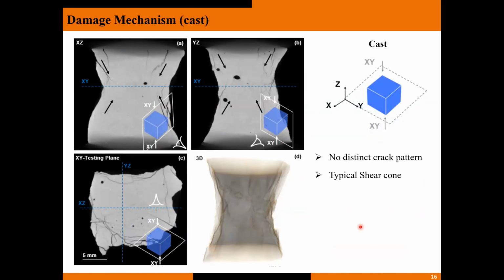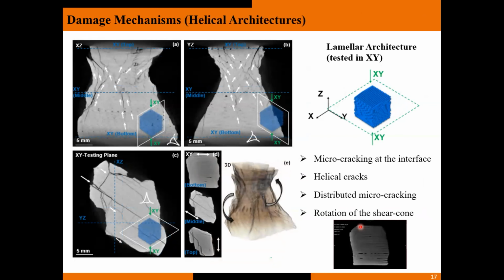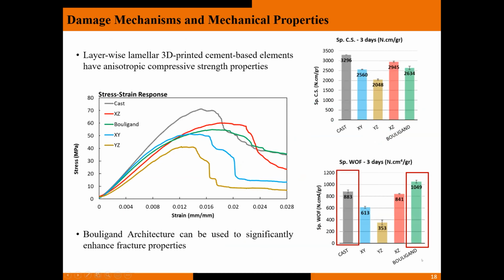Then we focus on the damage mechanisms in these samples. As in cast, there was no distinct crack pattern, just localization of a crack in form of a shear cone, as opposed to a helical architecture in this case, where we observed numerous microcracking at the interface and a helical exterior crack pattern. So in other words, we were able to distribute the microcracking similar to those we observed in the flexural test, but here we're looking into compression, which we later found helped also improve the toughness of the material, intrinsic toughness of the material, compared to the cast counterparts. The graph right here is comparing the area under the curve between the cast and the Bouligand architectures.